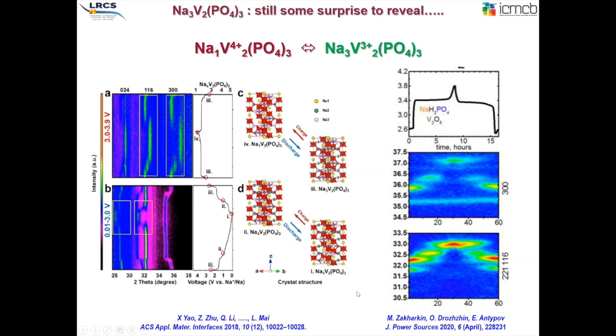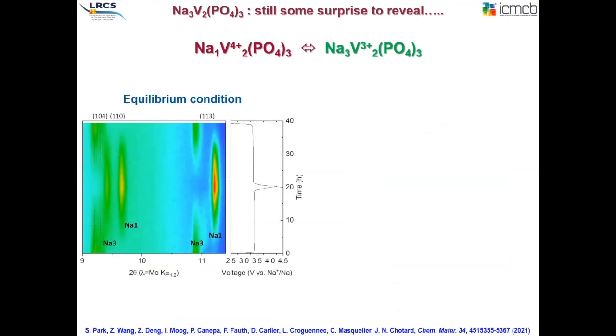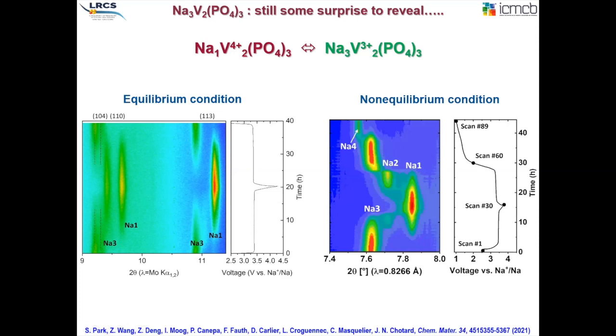This was really intriguing for us, and we worked a lot at the ALBA synchrotron to try to identify this weird intermediate phase. At slow rate, in equilibrium conditions, we go basically from the Na3 to the Na1 phase through a two-phase reaction that occurs at 3.4 volts versus sodium. When the battery is cycled at a higher rate and in different conditions, we indeed also saw the appearance of this Na2 phase at mid-charge. This was really a surprise for us and a confirmation of what had been published by the Russian group.